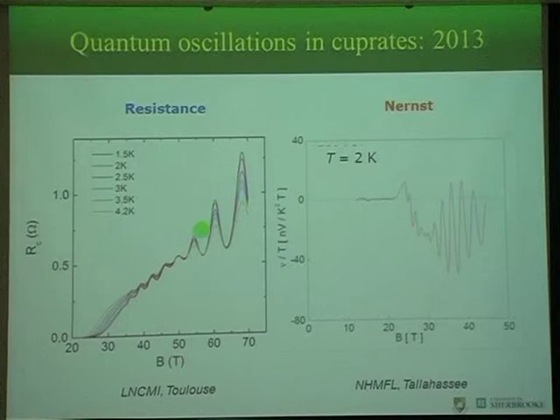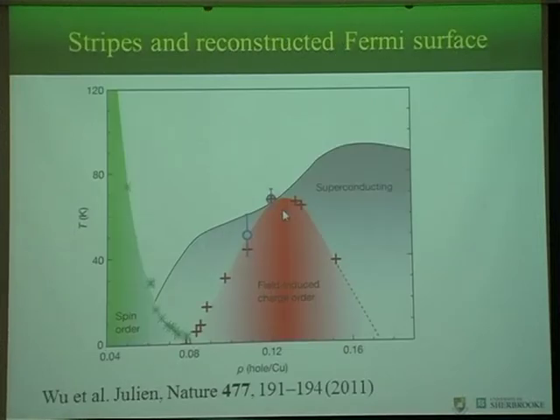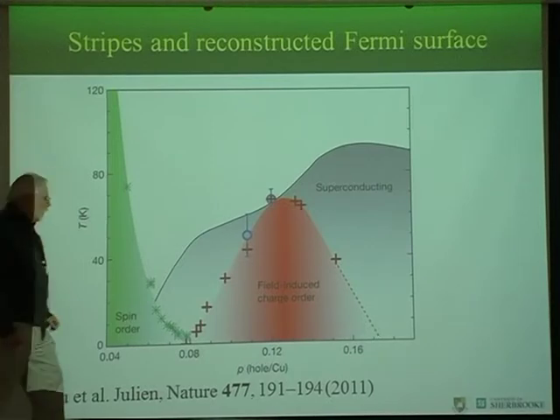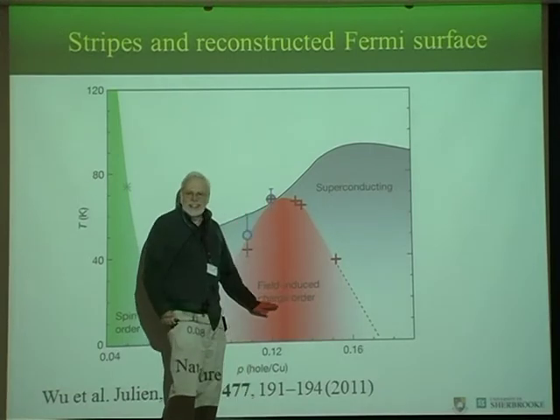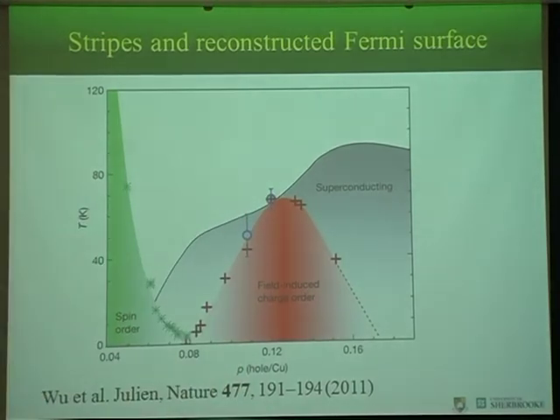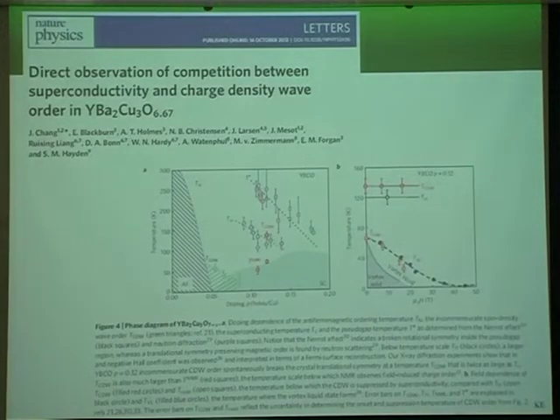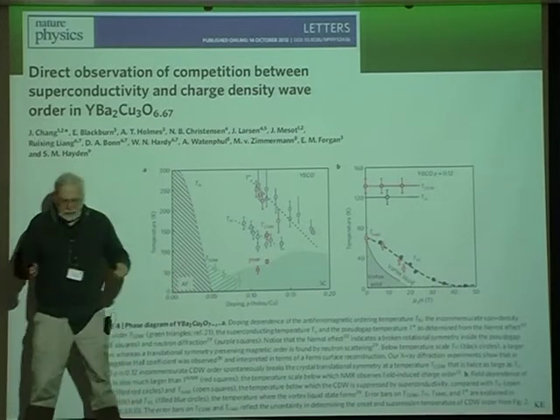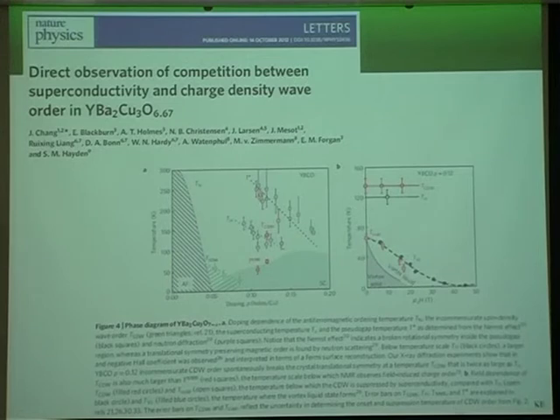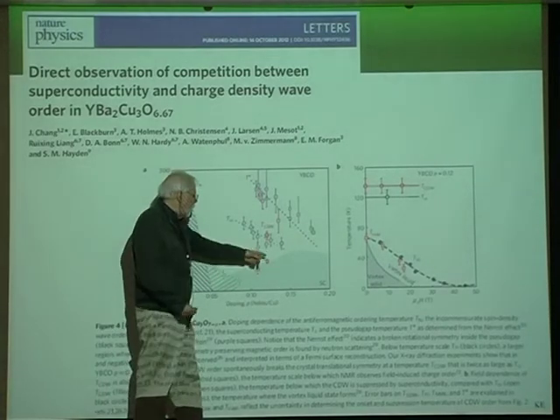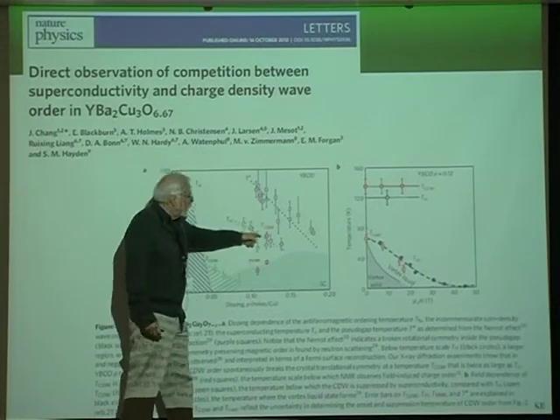Now in 2013, one can do much better with the c-axis resistivity and the Nernst effect. These oscillations are seen everywhere. And Marc-Henri Julien in France pointed out through NMR experiments that there was a field-induced charge order in this region in 2011. Since that time, there's been a flurry of experiments. I cannot quote everybody, but here is just X-ray scattering. They saw peaks that appear at a wave vector, really like an order parameter. So they found a transition. Here, this is this CDW.